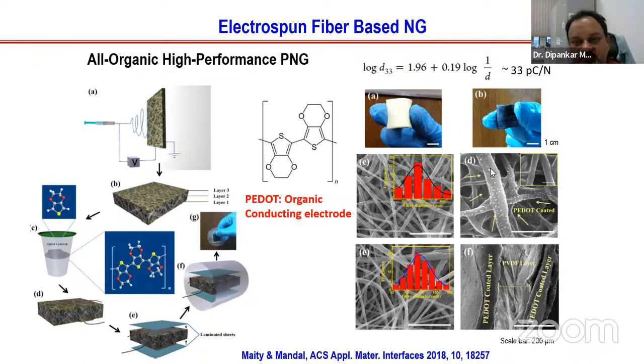kind of spongy. So what we did, we have shown an all-organic approach. We used an electrospinning process and tried to deposit fiber coated with conducting organic materials. This is the chemistry part, a very interesting chemistry. We made a strategy so that our fiber is coated with conducting polymer. I'm not discussing it in much detail, but those interested can get all the detail from here. You can see the PVDF fiber was coated with PEDOT:PSS, which is conducting in nature. So this white fiber turned into the black one. That means it is composed of two electrodes, and in the middle we have a piezoelectric.